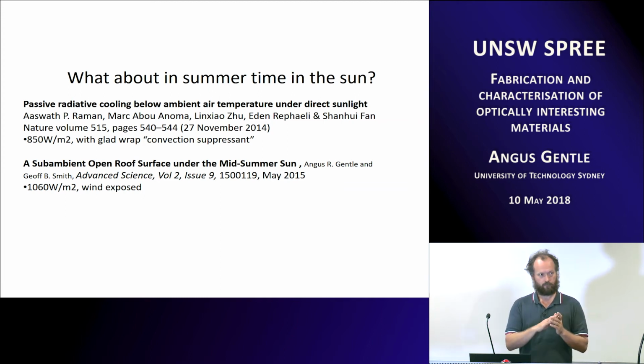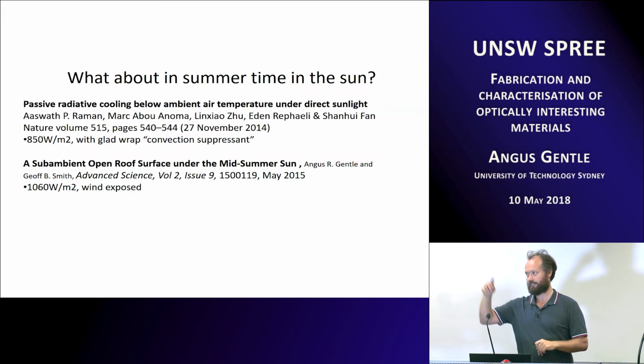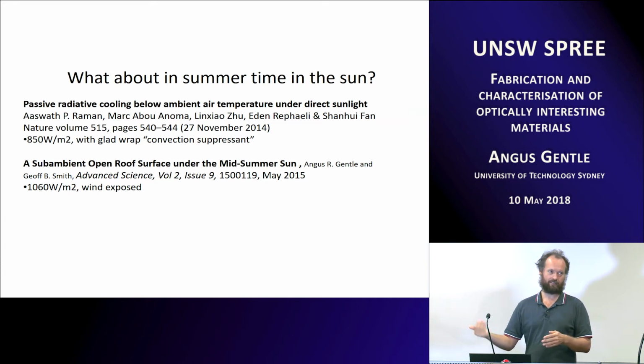We went for a fully open surface, like a roof surface, to see if you can get below ambient with wind warming you back up at the same time, and in actual full sunlight. So we had 1,060 watts per square metre, and you can actually still get below ambient. The length of time you can stay below ambient gets limited by how much dirt you end up picking up. Because we're based off Harris Street, most surfaces get pretty dirty there. So you see the temperature creep back up towards ambient, but for any surface where you're aiming for above 96% reflecting, it doesn't take very much to start to absorb that extra bit of heat.